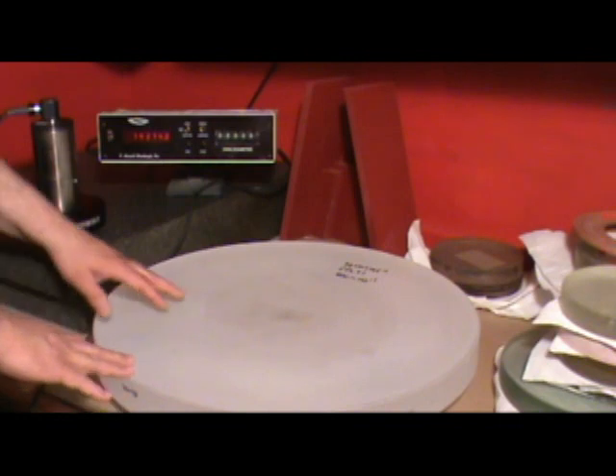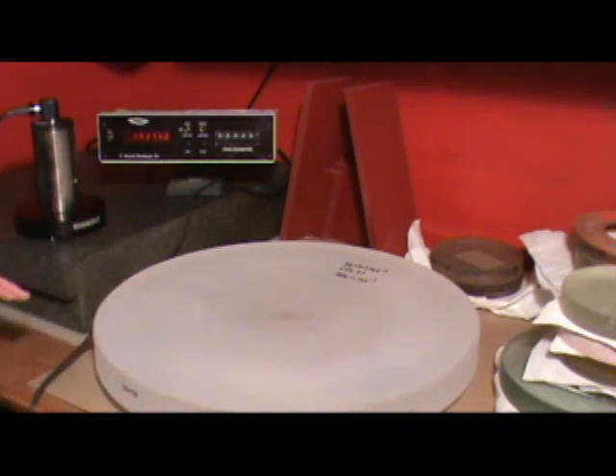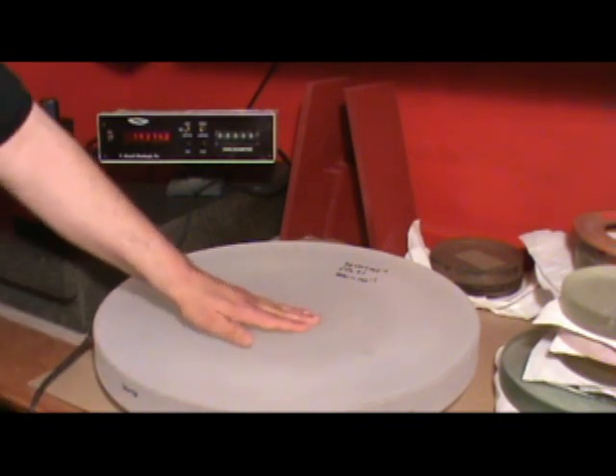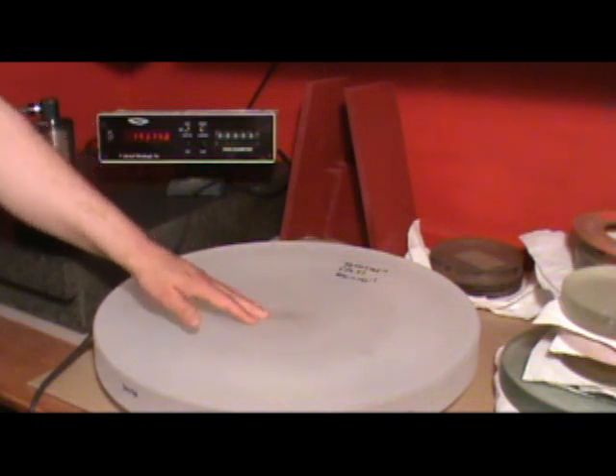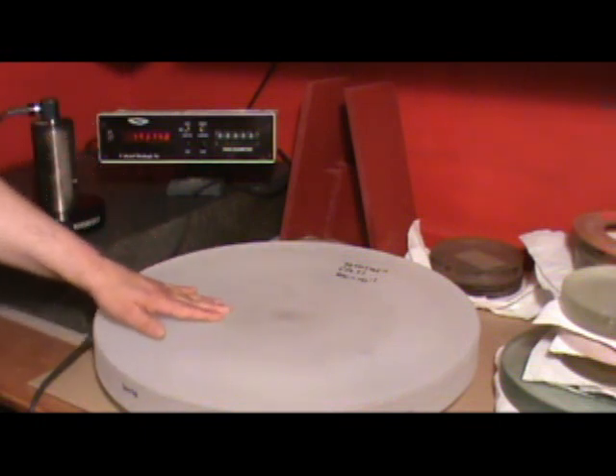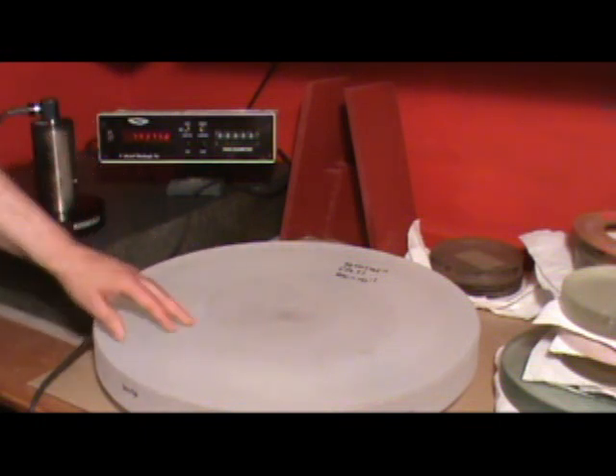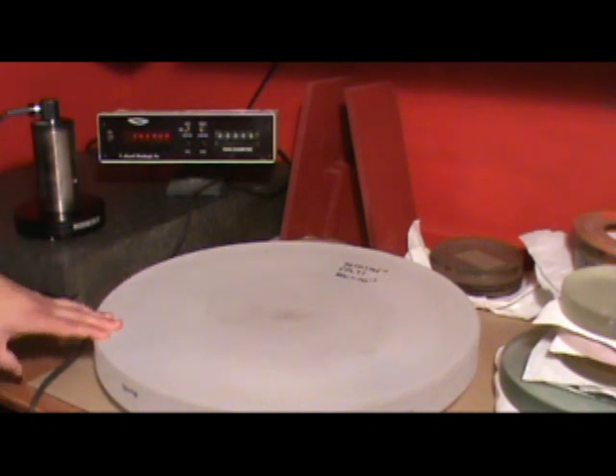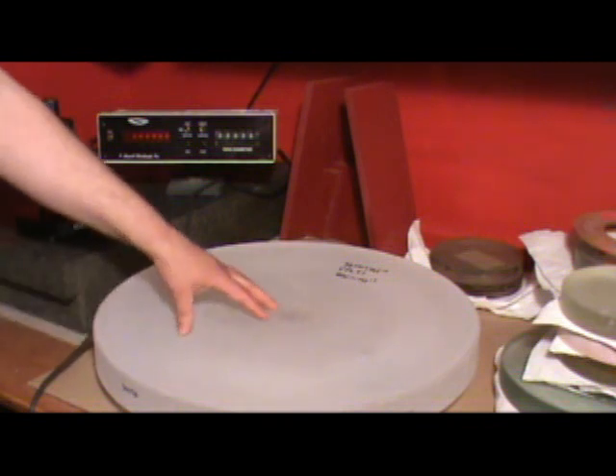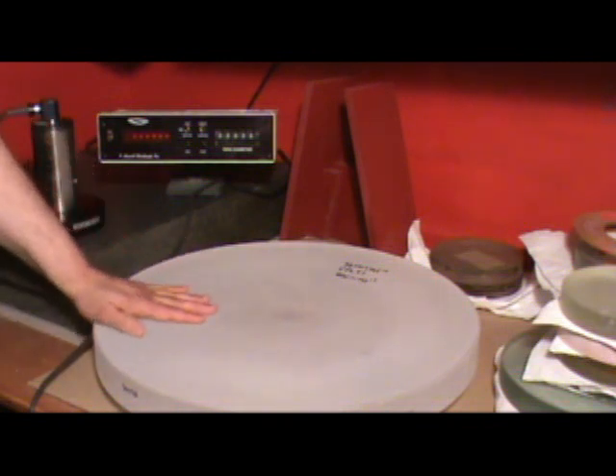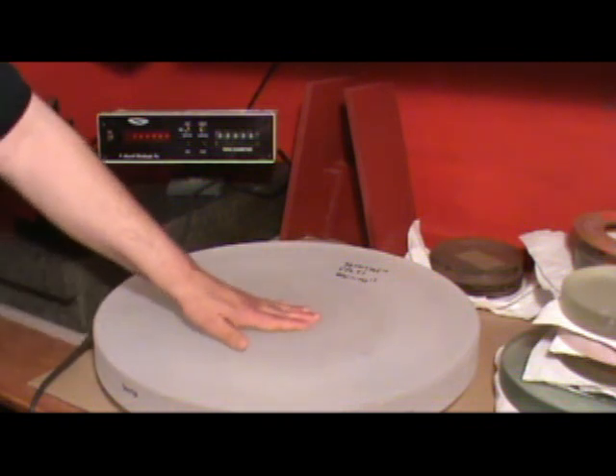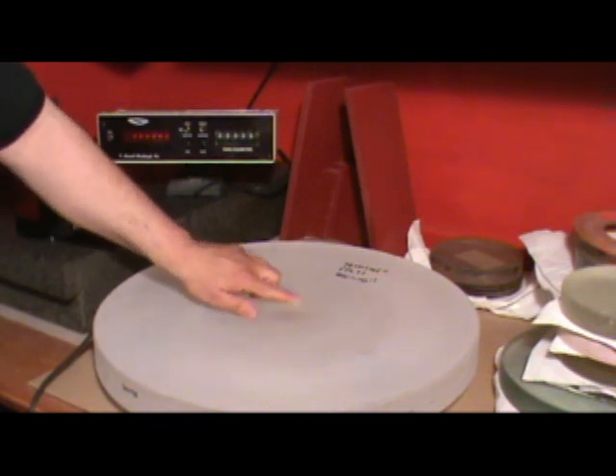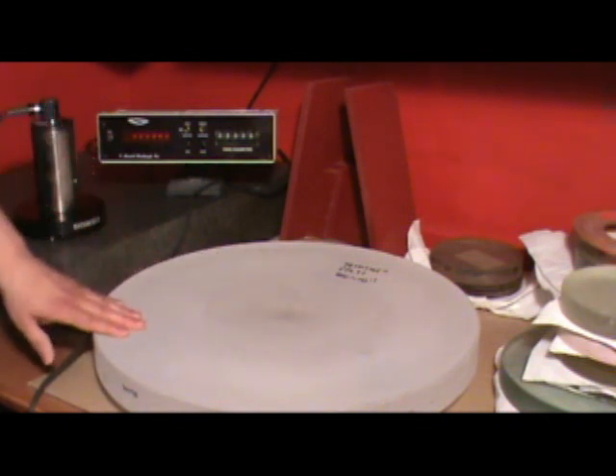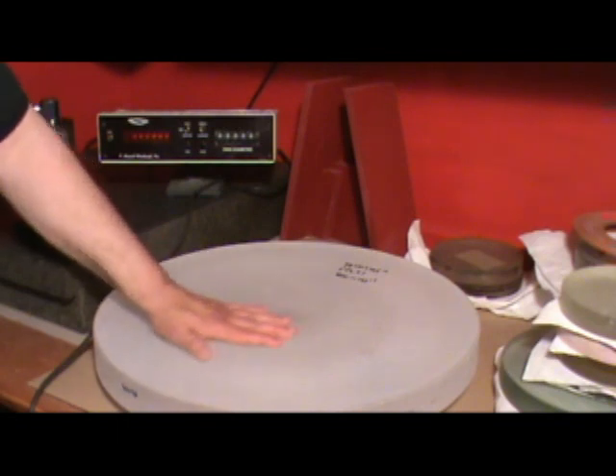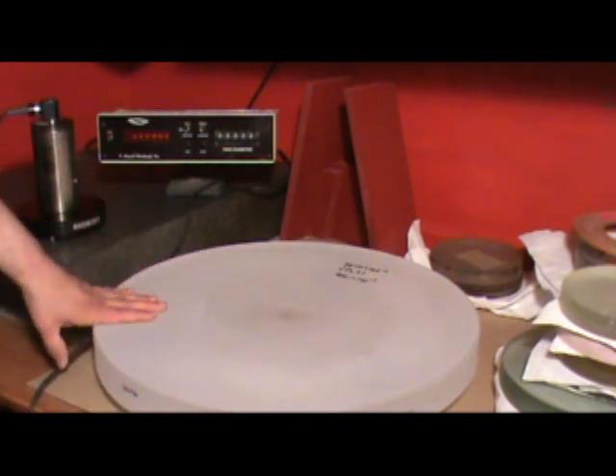Now I took the measurements on this mirror earlier and took the averages, and the average in the center is about 126 inches. At the 50% zone, it's about 151 inches, and out at the edge, it's about 145 or 146 inches. If you average all of those three, it comes pretty close to our 140 average that we're looking for. The center is just slightly too deep, plus there's a little artifact left there from the generator itself, which we'll clean up right away as soon as we start grinding on this.